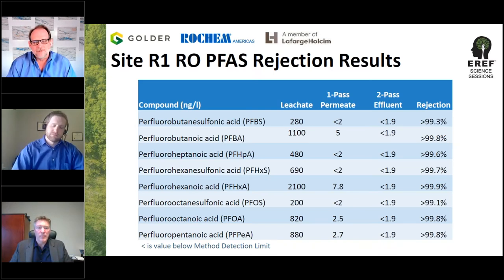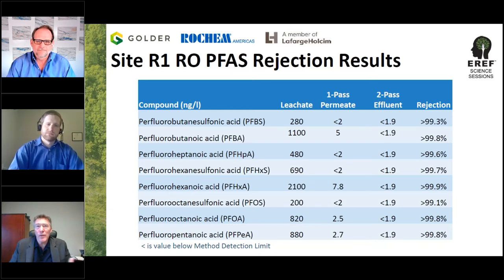Any organic compound, in our experience, more than about 100 molecular weight is effectively 99% removed by reverse osmosis. The smallest of the PFAS compounds that I've been able to come up with right now are about 400 molecular weight, so it's going to do a very good job of taking all these compounds out. Now, Pat, I'm curious whether you thought this was an expected result, because the design of reverse osmosis already catches a lot of contaminant molecules. When this PFAS issue first came up, what were your thoughts? Were you thinking this is going to do a pretty good job, or were you in the I'm not sure camp?